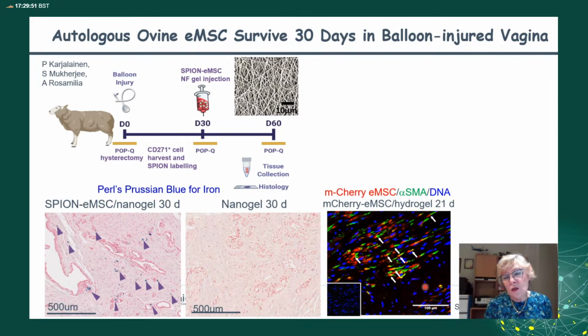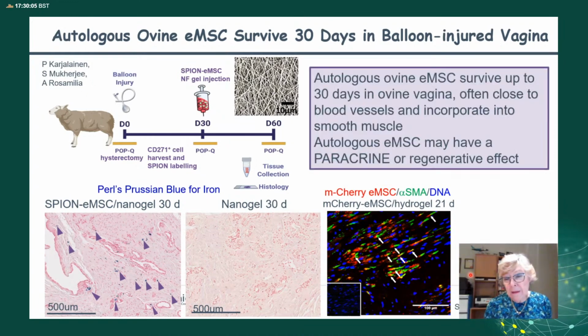And we've also looked at the mCherry, as I showed before, in an injectable form. And you can see, and this is in a smooth muscle bundle of the muscularis, the green stained smooth muscle actin cells also showing mCherry labelling. So autologous EMSCs, again, they survived up to 30 days in the ovine vagina, here often close to blood vessels and sometimes incorporated into muscle. So these autologous EMSCs may have a paracrine or regenerative effect.